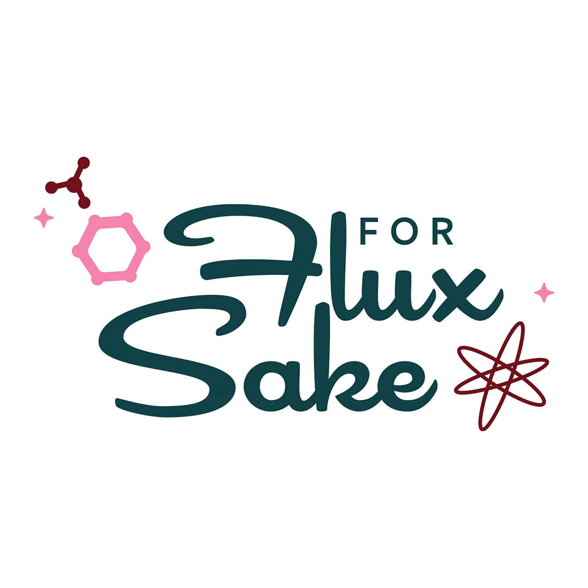When I say I fire fast, I fire 300 degrees C per hour to 100 degrees under peak. So for a cone 6, that would be 1143. And then I will switch to 150 degrees C per hour to 1222. And that will give me a perfect cone 6. And we're doing a bunch of those. They work fine. But if you are relying on that button that says fast firing, you are destined to fail. Why have they done this? I have no freaking idea.